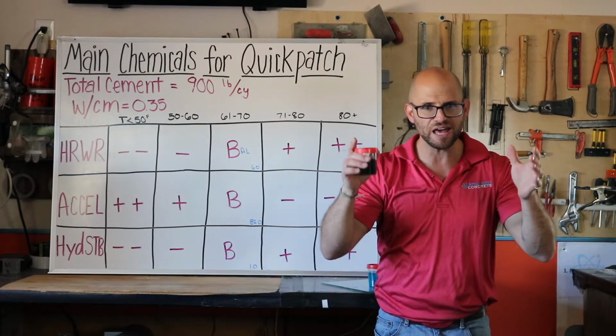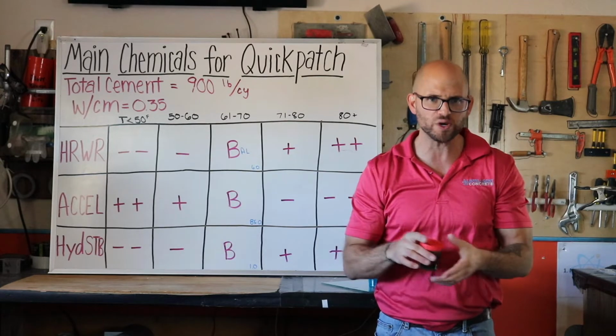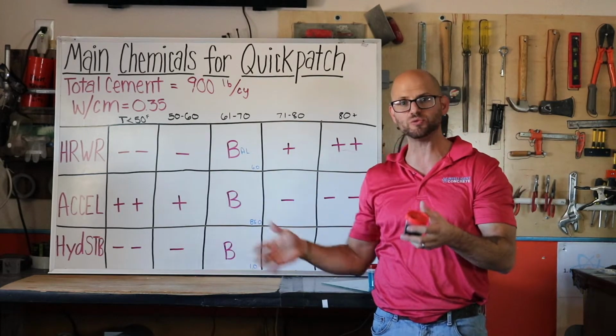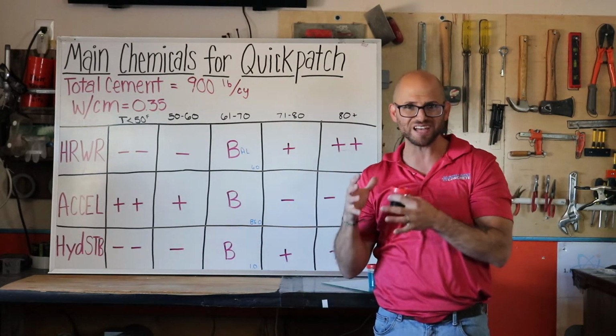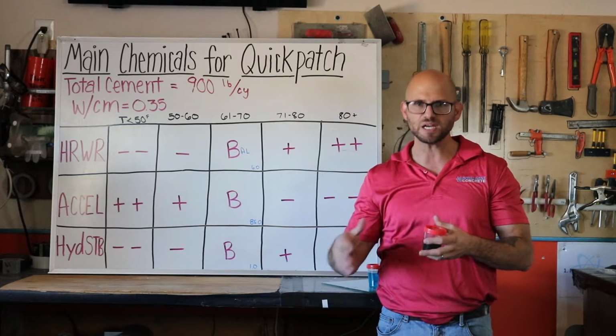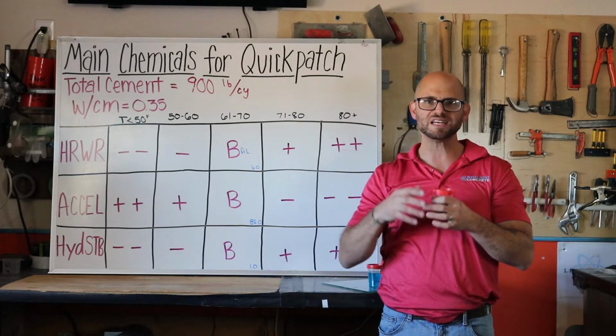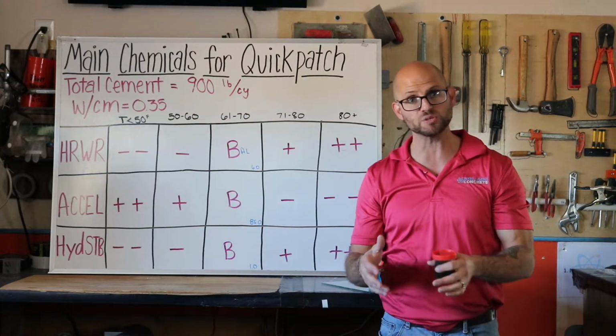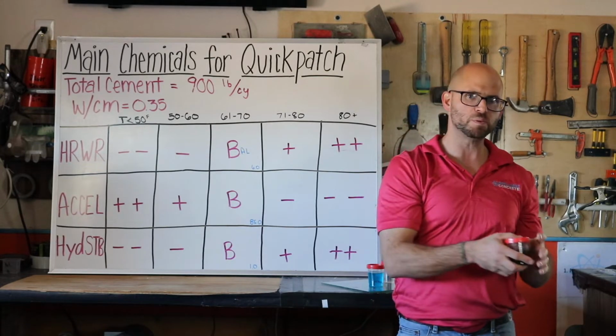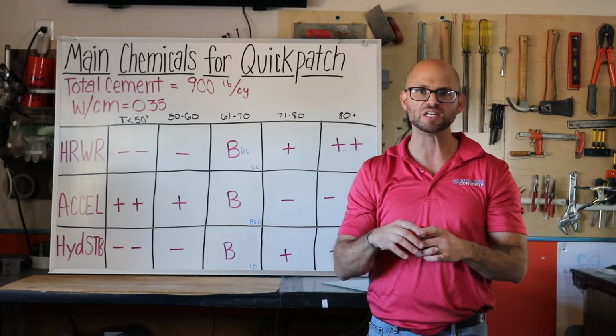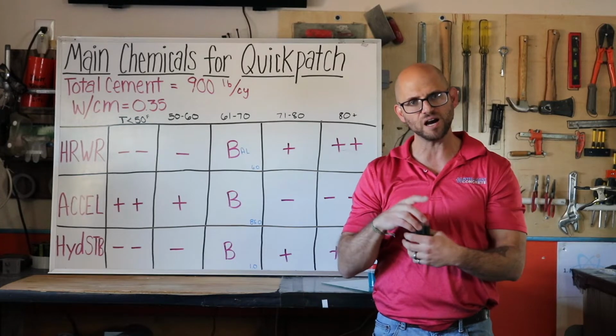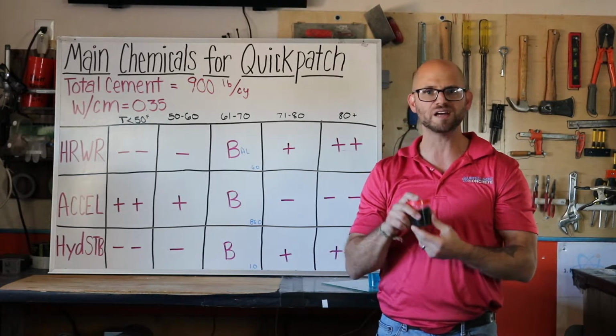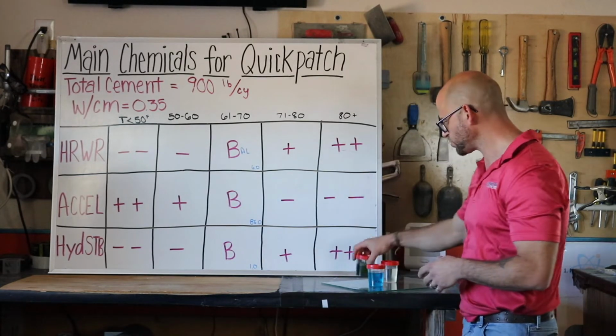So we start out at a 24 to 26 inch spread, and as we go through that slump life, we start tightening up, but we don't tighten up to the point where the concrete is unmanageable, and we don't loosen up to the point where we start seeing segregation. So the use of a nice concentrated, robust, high-range water reducer is important to create that.